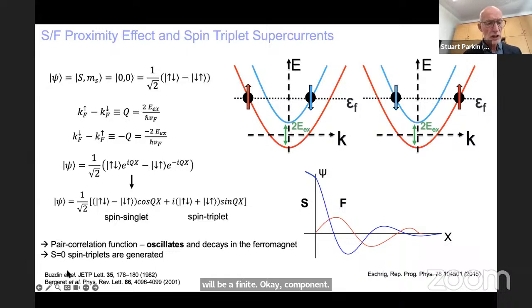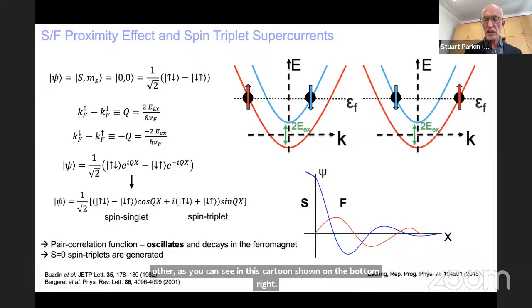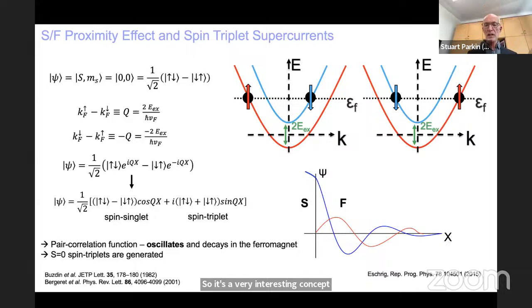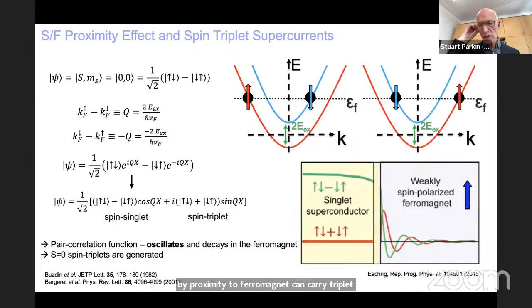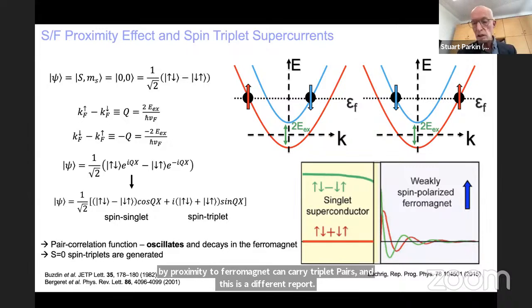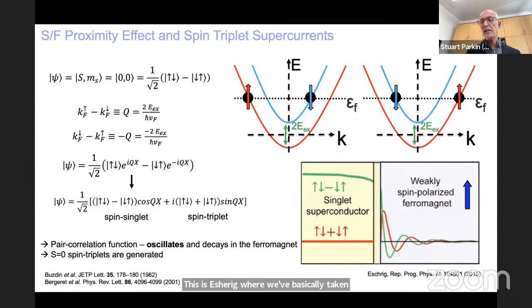And it turns out this is originally work by Buzdin in 1982. He showed that you now form a superconducting condensate by proximity in the ferromagnet with both a spin singlet and a spin triplet component, which oscillate in magnitude out of phase with each other, as you can see in this cartoon shown on the bottom right. So it's a very interesting concept that a superconductor by proximity to a ferromagnet can create triplet pairs. And this is a different report. This is Eschrig, from his review. And you can see then the green is the singlet component of the superconductivity, and the red is the triplet component. So you see that's what happens.